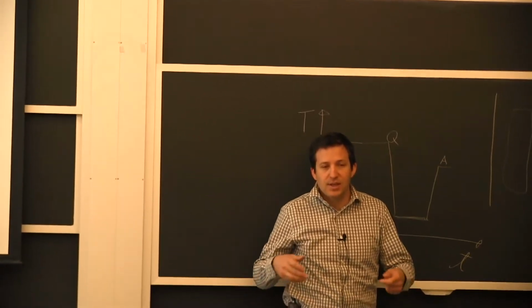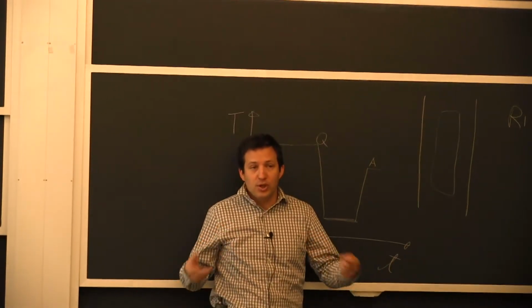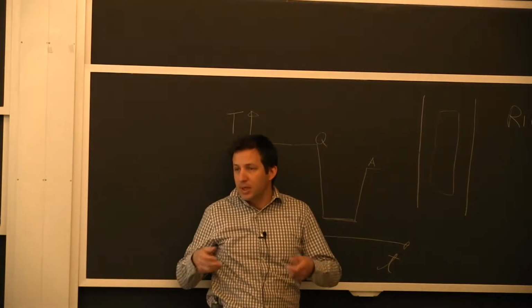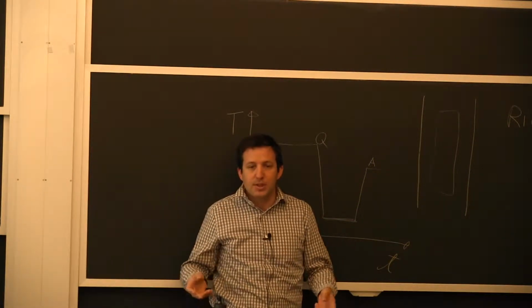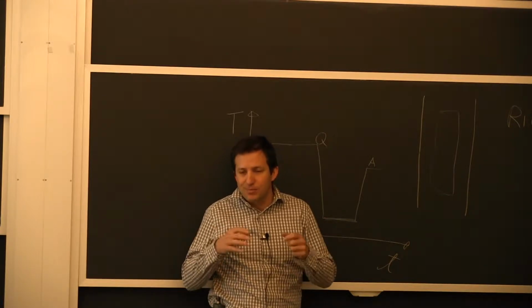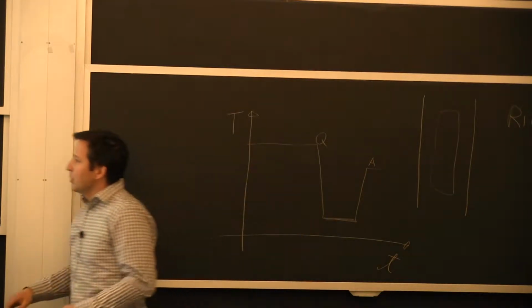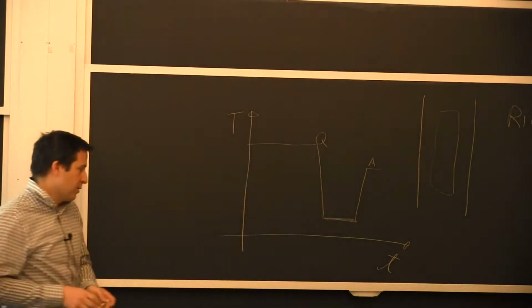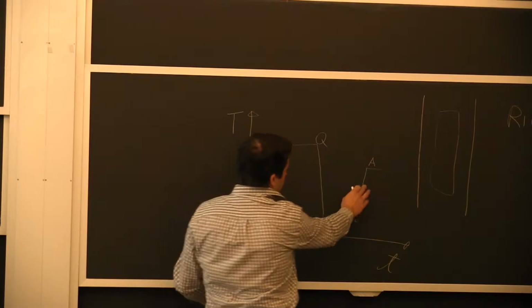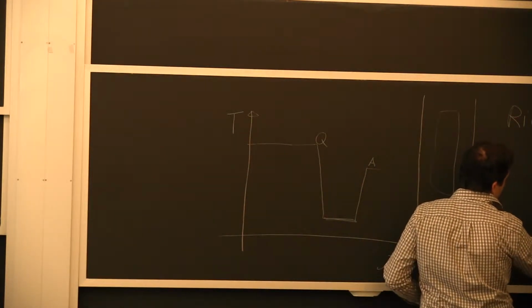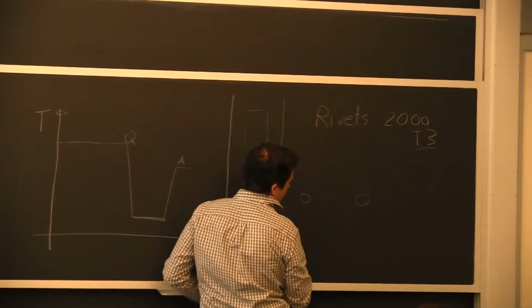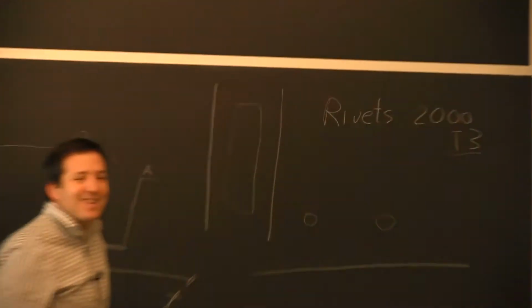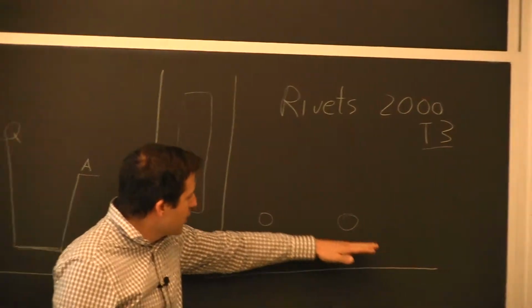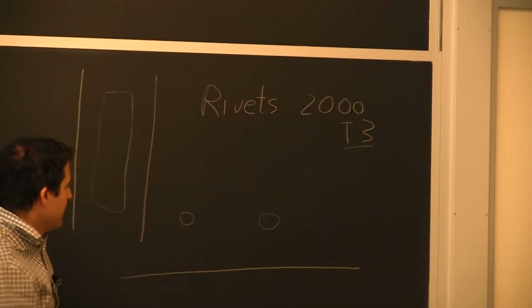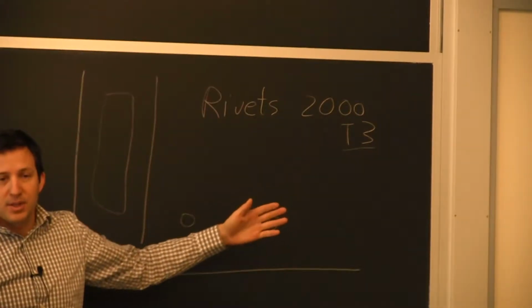So what happens with something this small is dislocations can still go through it. It will provide some friction. It will increase the properties a little bit, but because the dislocations go through it, it's only going to give you a limited amount of hardening. Then you go through a phase where they are a little bigger. So if we think about this, this is in the aging process. So if we have a particle, and say we have another particle here, the dislocations are always linear defects. So you have a line that's trying to come to these 2 precipitates. If it can cut through it, there's not much going on.